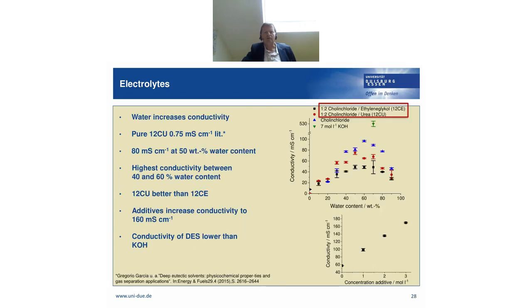So what we did, we tried to increase the conductivity because the conductivity is too low to have good test results in the zinc air environment. So we took mixtures of, for example, 1 part choline chloride with 2 parts ethylene glycol, abbreviated as 1,2-CE, or 1 part choline chloride with 2 parts urea, abbreviated as 1,2-CU. And you see the conductivity is displayed in millisiemens per centimeter over the water content. For example, we get conductivities of 80 millisiemens per centimeter at 50 wt.-% water content. So this is well above the value of 0.75 millisiemens per centimeter for pure 1,2-CU.